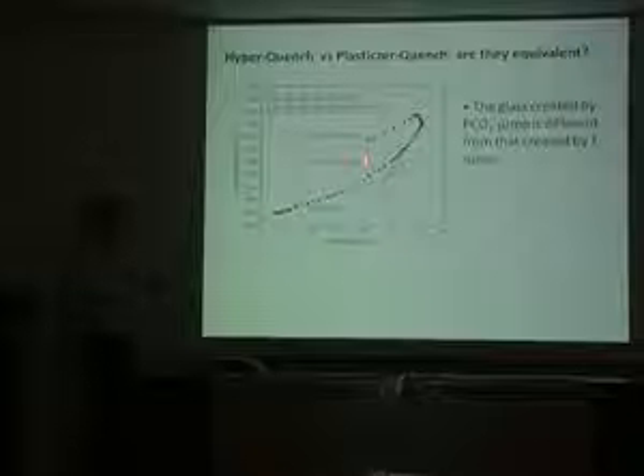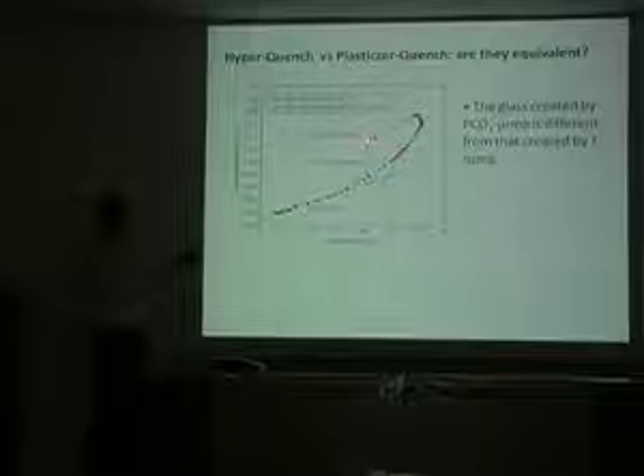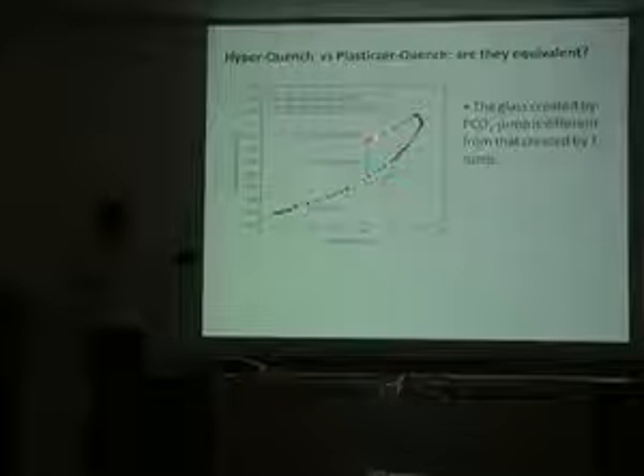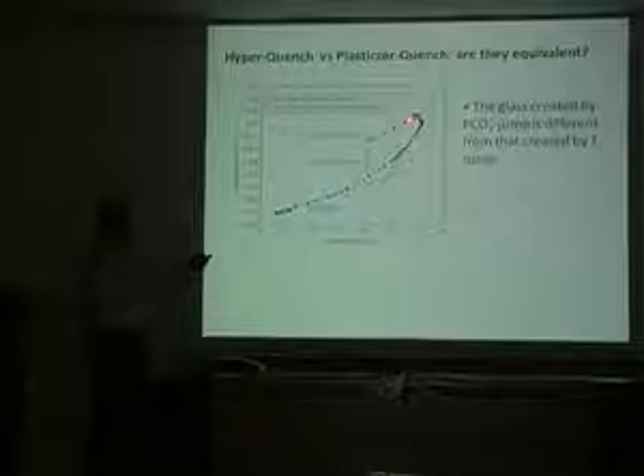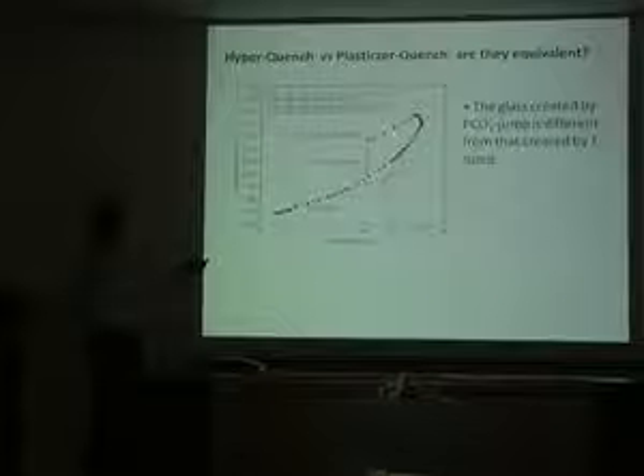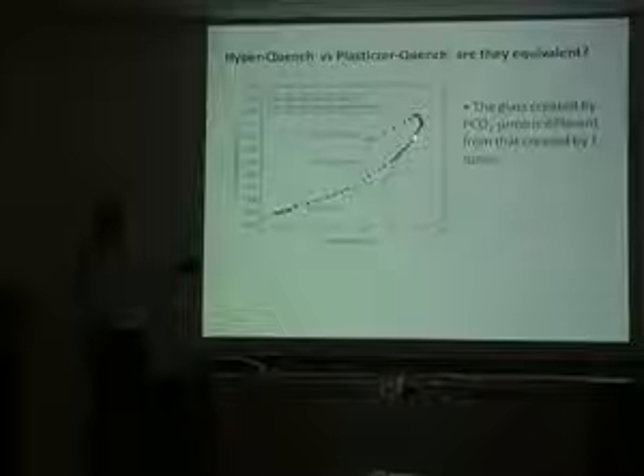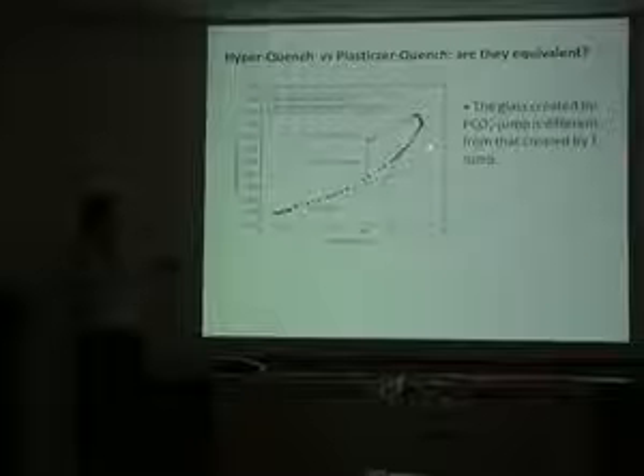We do a carbon dioxide pressure jump, and we create something with an excess volume compared to the normal glass behavior. And what we see is that it sustains that volume up to almost 80 degrees centigrade, where the TG is below 70. It sustains that volume and then collapses as we heat it. And then it comes back down, and it's on this glass line. So the glass created by the PCO2 jump is different from that created by the temperature jump.